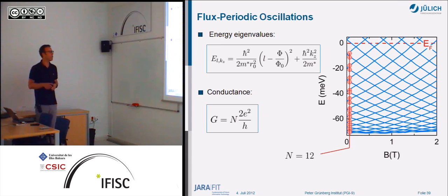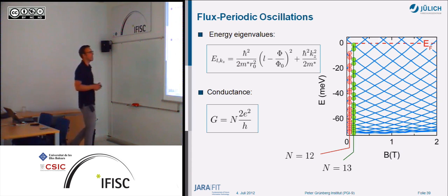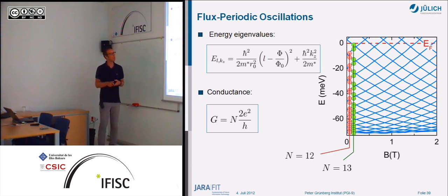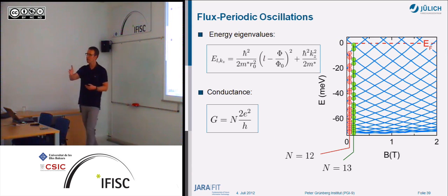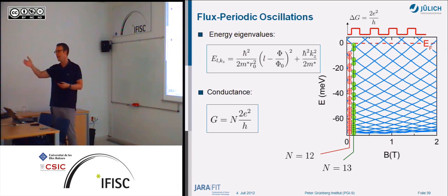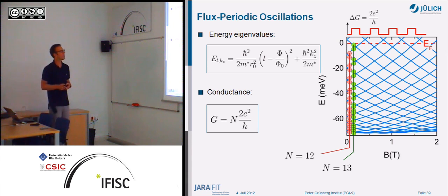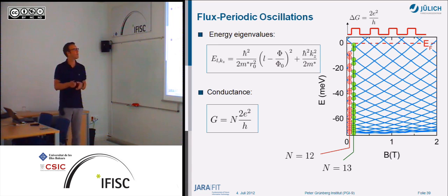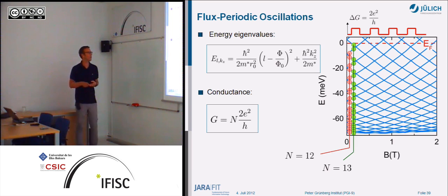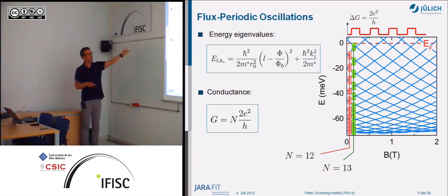And if you look now, how many states do we have which count here? For a certain magnetic field, if you count them, we have like 12 states here below the Fermi level. But if you increase the magnetic field, you end up with one more state here. Here you have 13, and this is going periodically because this structure is periodic. You're switching from one number of occupied states to a number higher by one. And so if you look at the conductance, ideally this conductance should be switched by one quantum back and forth, periodic with one flux quantum. So that's the idea of how you can explain the conductance here.